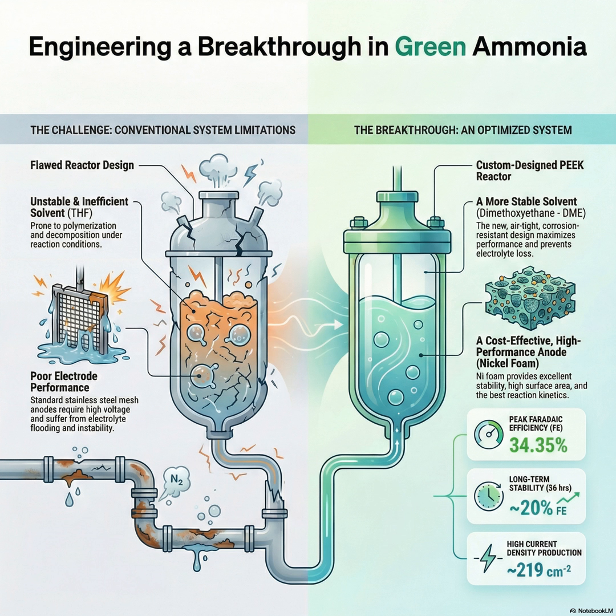But the truly game-changing number, the one that really signals this might be viable, is from the long-term stability test. Okay. Remember the 5 to 8 minute failures of the past systems? I do. The UIC team ran their system continuously for a stunning 36 hours. 36 hours, that's more than a full day, and it was stable the whole time. Stable operation, maintaining a consistent ammonia selectivity of around 20% FE, that's the difference between a lab curiosity and a real continuous manufacturing process. It's a breakthrough.